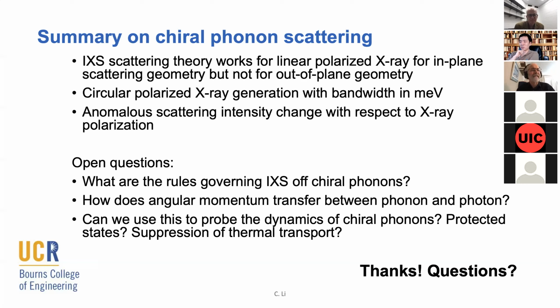Yeah, thank you, Brent. That's actually a very good question. We are puzzled with that too. This mode has to be very anharmonic. Even when we do frozen phonon calculation on that mode, we know the potential would be very far away from what you would see in a quadratic potential well. So we still don't know why, but my speculation is it has something to do with scattering phase space. Even if this mode is highly anharmonic, since there's no lower energy mode this phonon can easily decay into, that might have something to do with it.